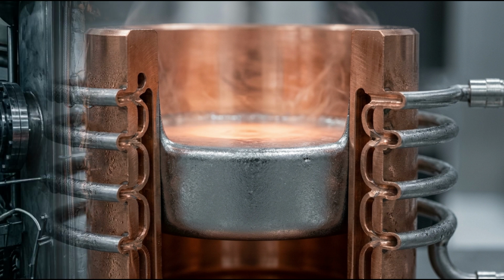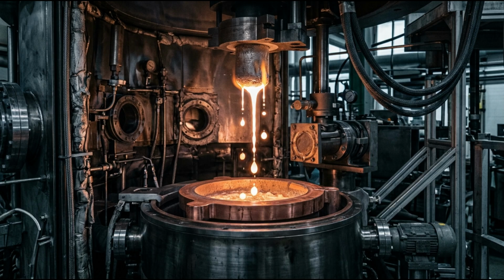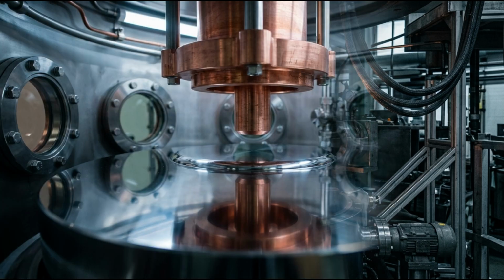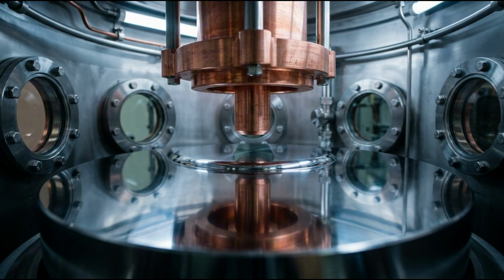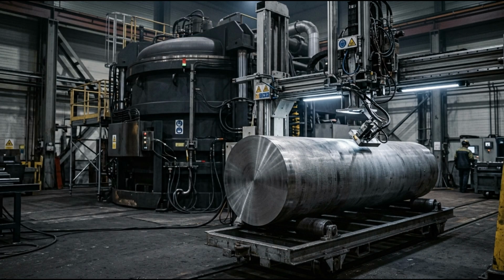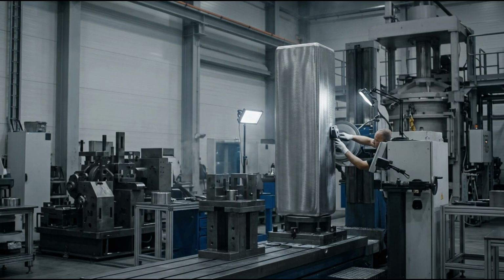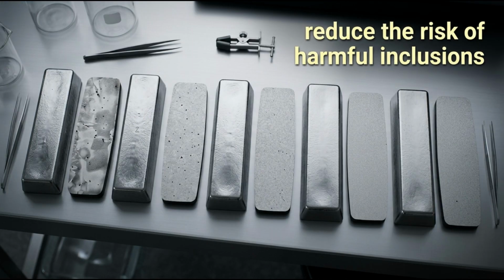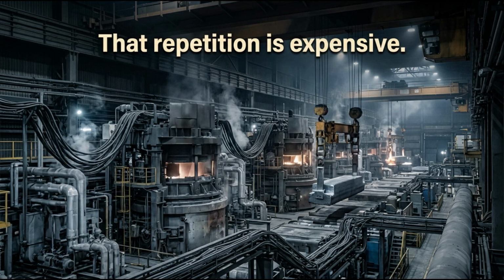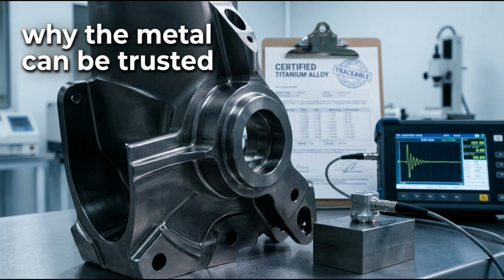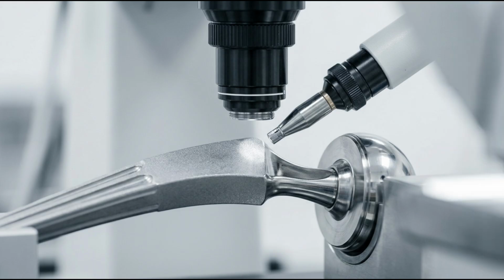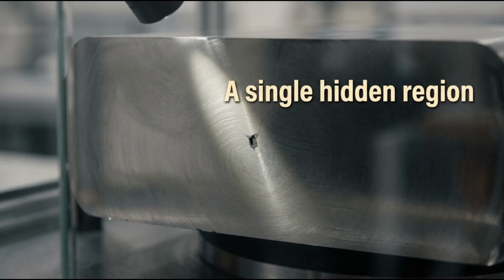Even here, the factory is still solving the same hidden problem. The equipment must touch the titanium without becoming part of it. For demanding grades, one melting cycle may not be enough. The first ingot can be removed, inspected, conditioned, and used as the electrode for another vacuum arc remelting cycle. Some critical materials may undergo multiple melts to improve chemical uniformity and reduce the risk of harmful inclusions. That repetition is expensive. It is also why the metal can be trusted. An aircraft component cannot be reliable only in most places. A medical implant cannot be clean on average. A single hidden region with the wrong chemistry can matter more than the thousands of kilograms of metal around it.